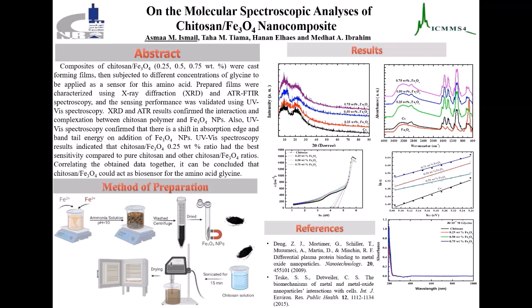Also, UV-visible spectroscopy results indicate that chitosan with a 0.25 iron oxide ratio has the best sensitivity compared to pure chitosan and other chitosan iron oxide nanocomposites. Correlating the obtained data together, it can be concluded that chitosan iron oxide could act as a biosensor for the amino acid glycine.